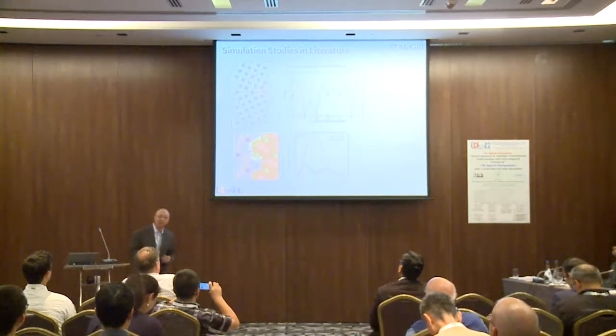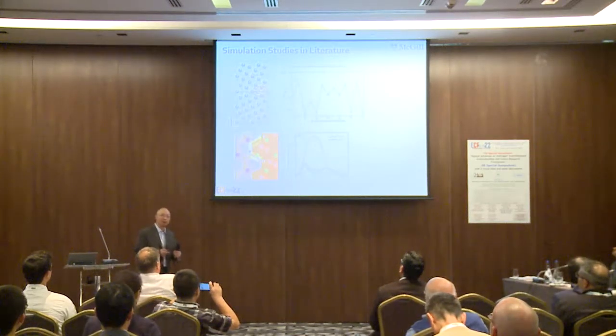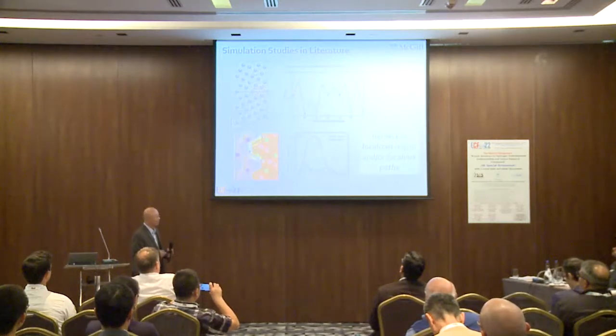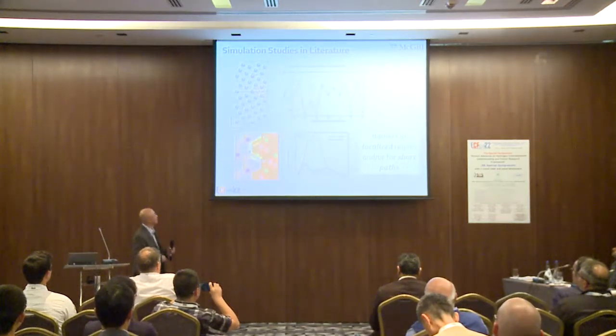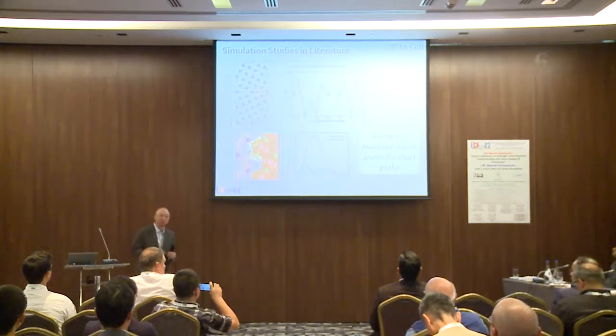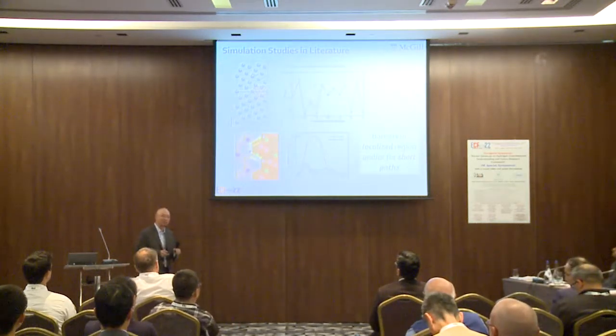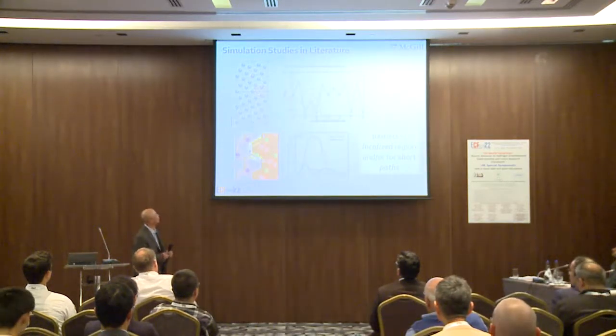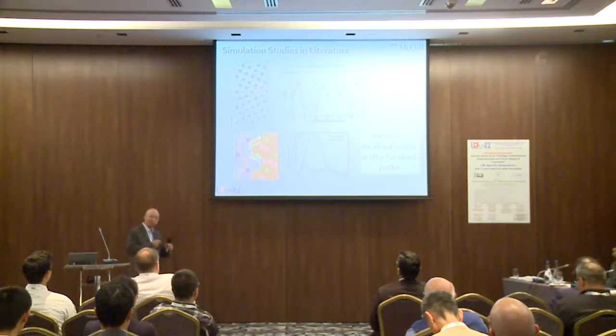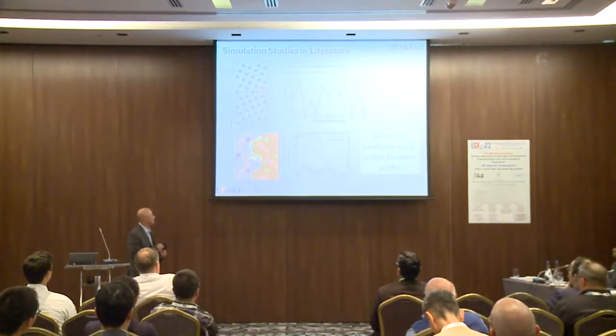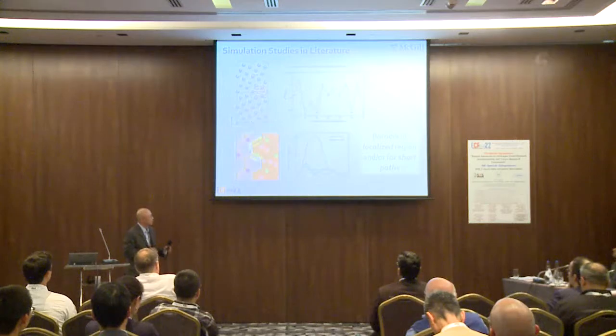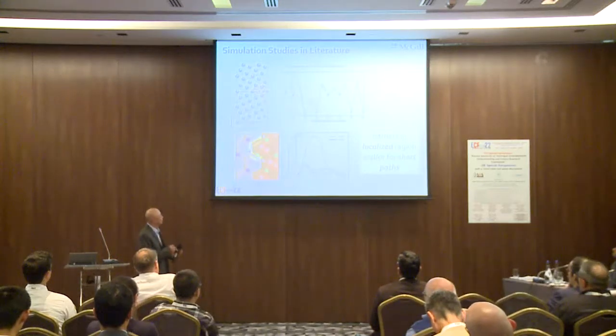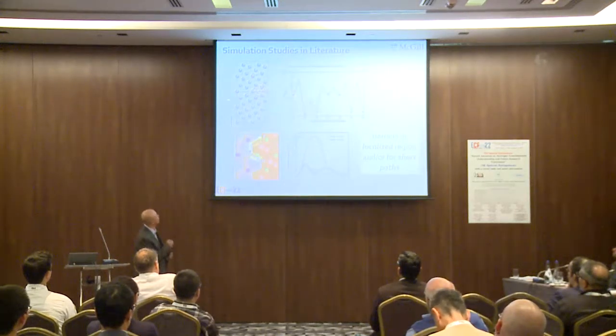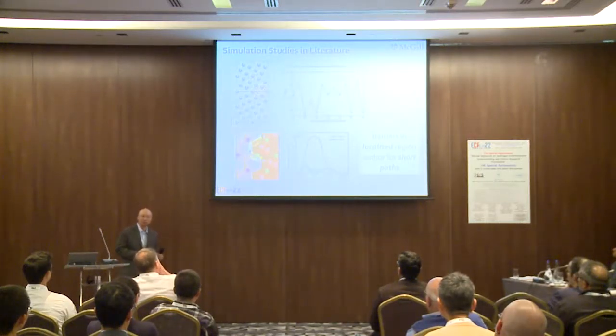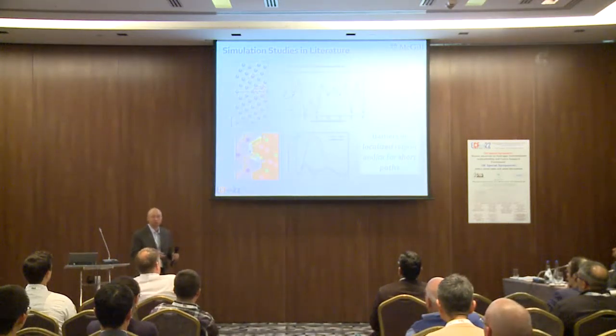There have been many theoretical studies looking at local barriers, but the problem of those, I shouldn't say problem, is that it's quite common because most of the studies are DFT calculations. So it's kind of confined by the calculation itself. And then for convenience, the study is mostly localized at a particular region at the grain boundary. You can see there's a high barrier path and low barrier path. But still, it depends on how you interpret the results. You can have different conclusions from the simulation, and it doesn't cover the whole grain boundary. So that's kind of the motivation. I basically quickly go through those slides, and there's a motivation for our study.